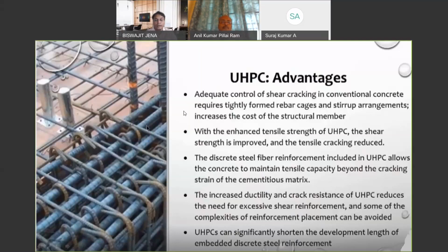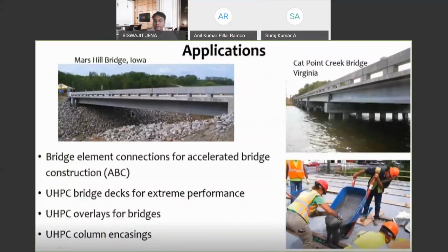So some applications are there with enhanced tensile strength. You can reduce shear cracking by improving the shear strength, and tensile cracking is also reduced. The discrete fiber reinforcement, steel fibers spread in a discrete fashion in ultra high performance concrete, helps in maintaining the tensile capacity beyond cracking, which means you have high ductility of the member. And if you have such a very high strength of concrete, the development length for your rebars can be reduced.